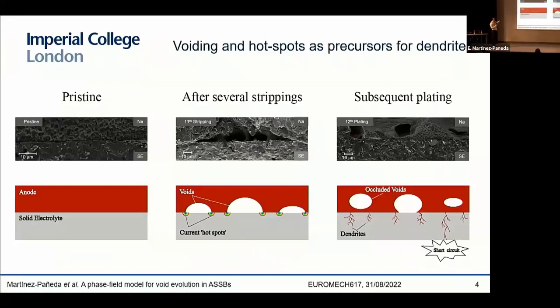So initially you have an almost pristine interface between the lithium metal anode and the ceramic electrolyte. But then every time you discharge, you have stripping, that is, you are removing lithium, and therefore you're generating those voids that you see there. And every time you charge, you have plating, that means that you're depositing lithium, and therefore you are making those voids smaller, and eventually you're even isolating those voids. So you're creating these occluded voids that are isolated from the interface.